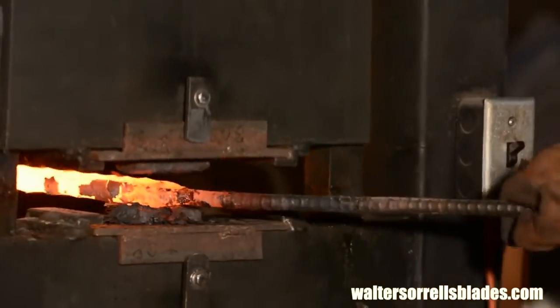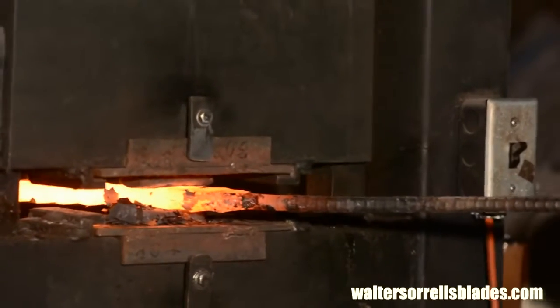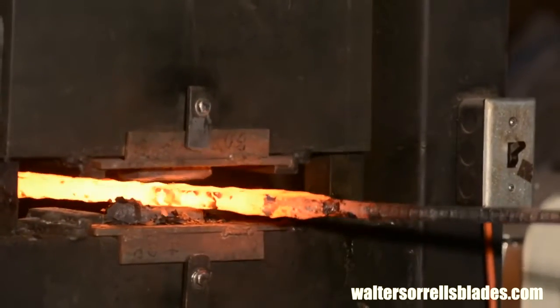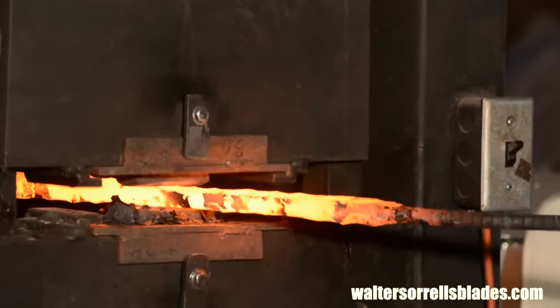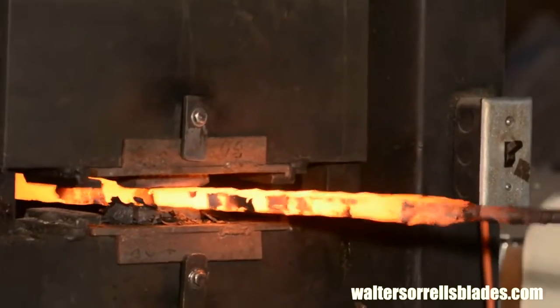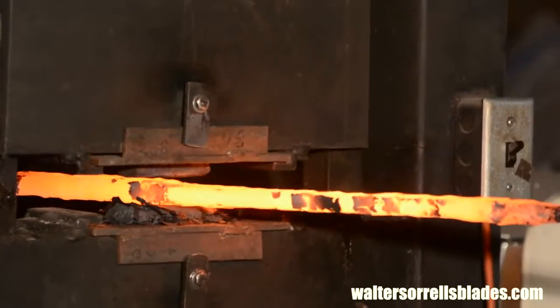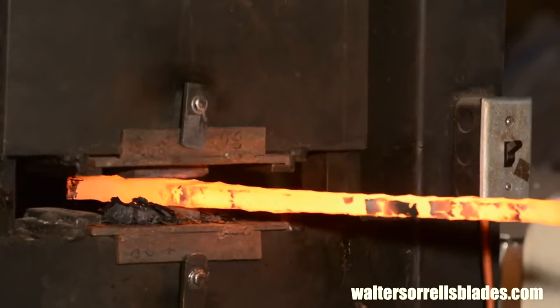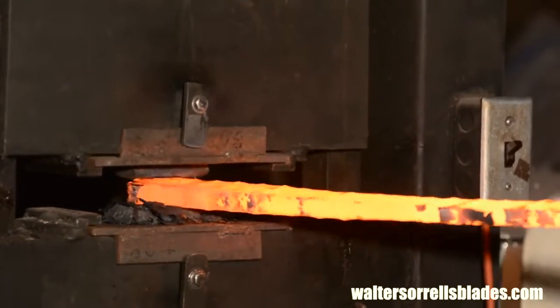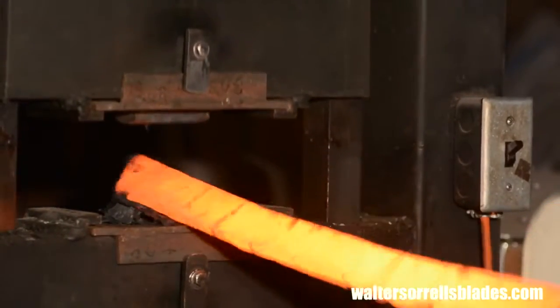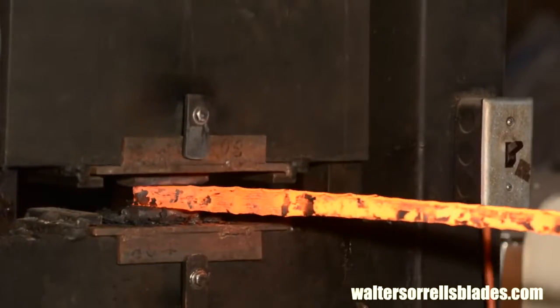You'll notice that after each pass as I'm drawing it out, I've flipped the blade. This keeps it from bending too much due to the slight difference in the profile of the top and bottom dies. Then I generally go at a 45 to 60 degree angle. This is more related to pattern development and not because it's the most efficient way to draw out the billet.